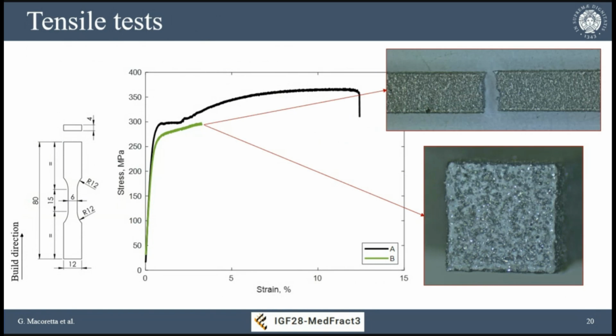This is also in particular because when we deal with elongation at fracture in tensile testing, a region of the specimen that is full of pores will for sure be the section where the defect localization occurs. Tensile testing exposes the worst region of the sample in terms of internal pores that already have dimples present, and so it significantly affects elongation at fracture, as happens also with different materials.